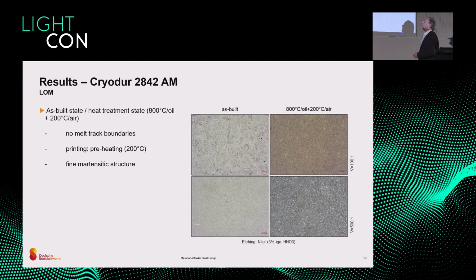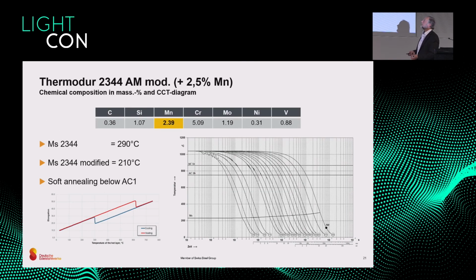In the as-built condition, you get a very fine structure, and you can use it as-built with a preheating of 200 degrees Celsius. You can use it even without. It's possible, astonishing, but you get a rather ugly structure. It's a mixed structure of martensite and retained austenite, and then you have to do a heat treatment.